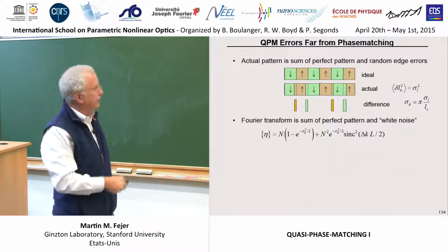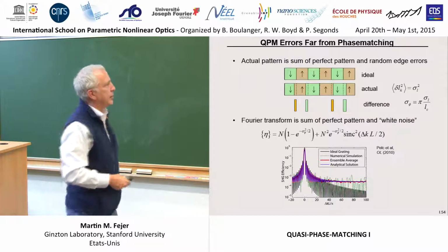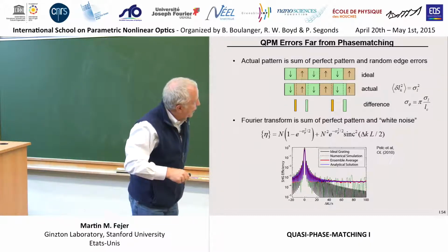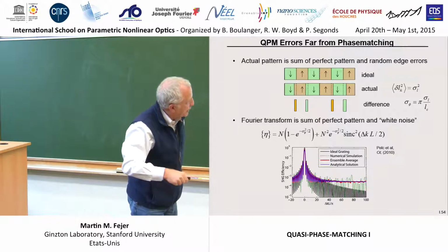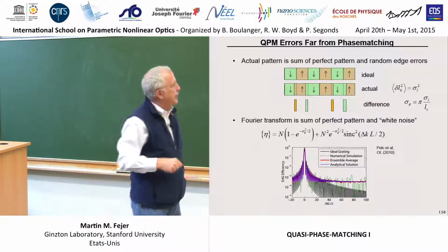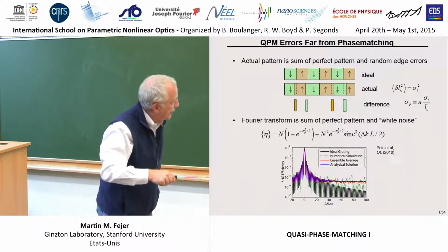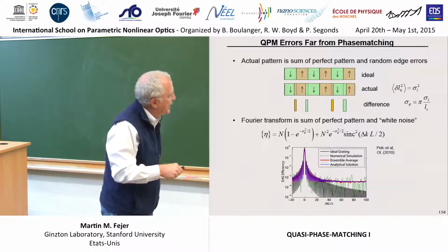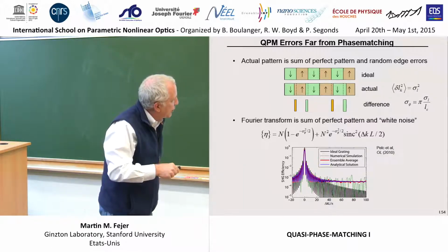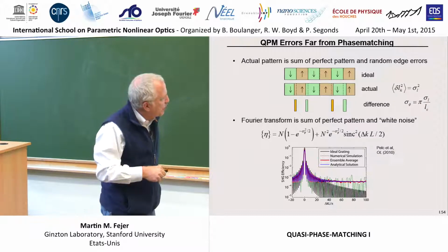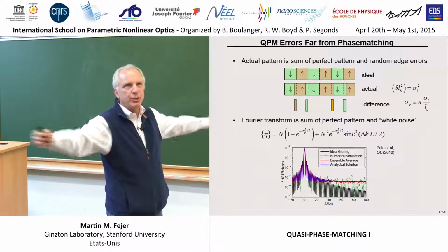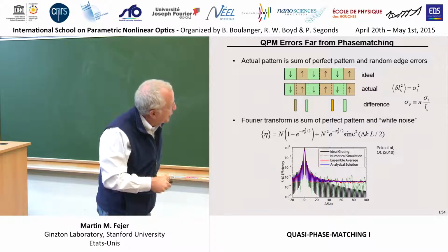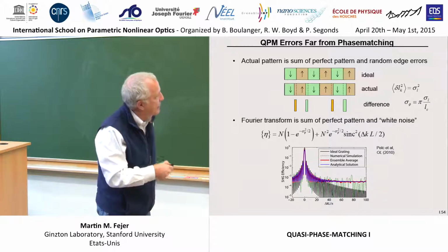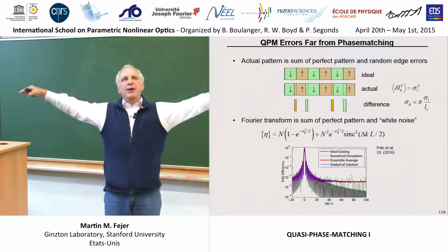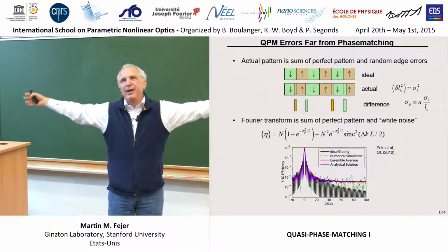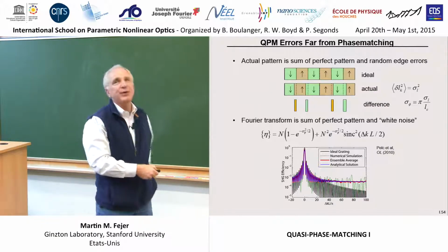efficiency. So if you look at the behavior of this thing, an ideal grating, though, so here's this SHG efficiency, here's delta K equals 0. In the perfect case, you have this sinc-like thing which is dying away in its wings. And maybe if there are some errors, you will reduce the peak efficiency a little bit. You won't increase the width because the long-range order is perfect from your lithography. But what you get is this pedestal, and this pedestal is this thing. And so the spectrum of this quasi-phase matching grating basically fills all of K-space. And so everything is a little bit phase matched by this grating.